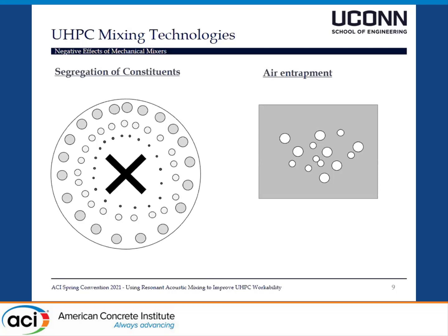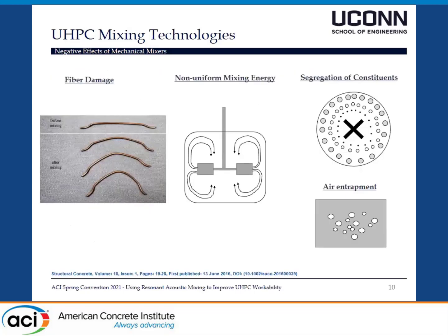Additionally, some other disadvantages are segregation of constituents during the mixing, such as particle size ranges. So near the impeller, you're going to have smaller particles, and the larger particles are forced out further away from the impeller. Additionally, you could have air entrapment due to the mechanical mixing tool, and so you'll have some unwanted air in the mix. So there are some inherent negative effects of mechanical mixers.